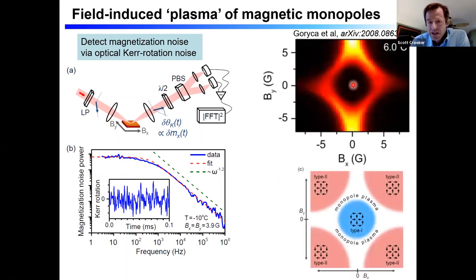So that's what we did. We built a very sensitive scanning Kerr-rotation noise spectrometer. We can measure fluctuations over six orders of magnitude in frequency and signal. And here's the data. So this is experimental data showing noise power measured experimentally as a function of applied field along y and x for square spin ice. And at zero magnetic field, no noise, everything's nice and stable, type one ordering. Large magnetic fields out here in the corners, again, stable, quiet, type two ordering, stabilized by field, but on the boundaries, things go crazy, okay? The system becomes very noisy, and this corresponds to monopoles being created and moving throughout the lattice.